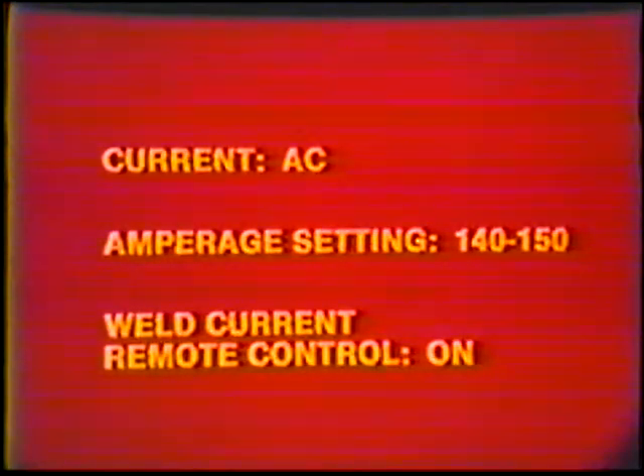Machine settings. Alternating current is used on aluminum. The amperage setting is 140 to 150 amps. However, the current is varied by turning on the weld current remote control and using a foot rheostat. The hot start is set to 4 to aid in starting the arc. The post purge is 10 to 15 seconds to cool the torch and prevent puddle oxidation.